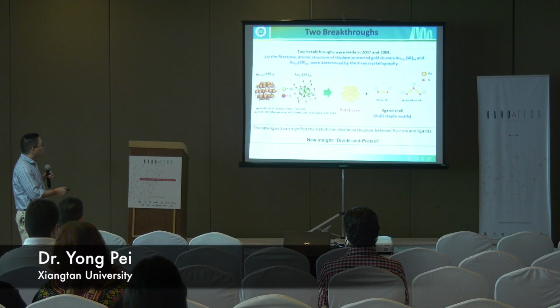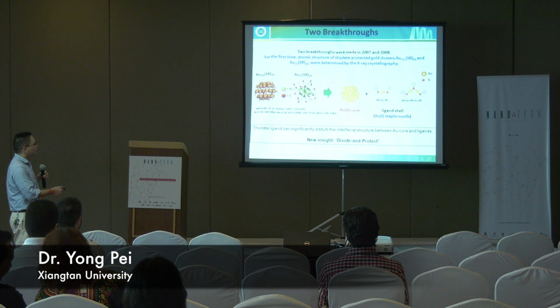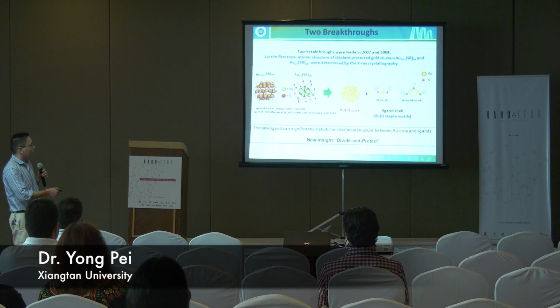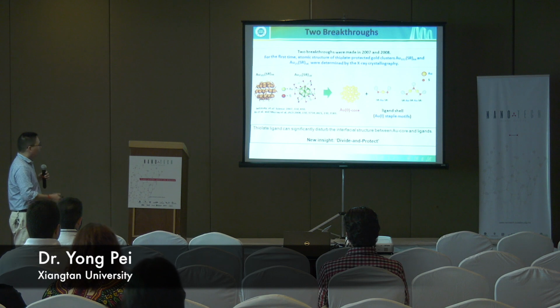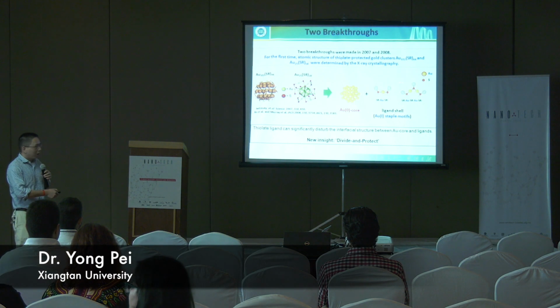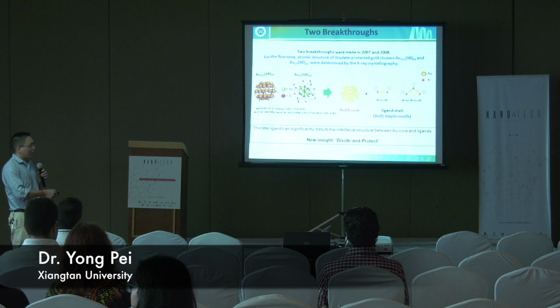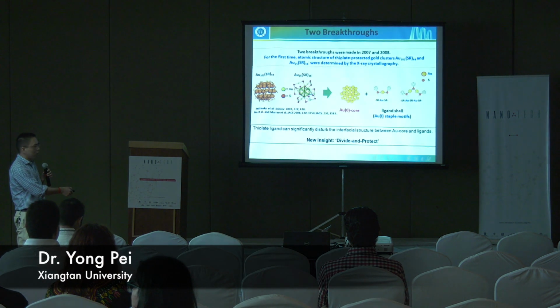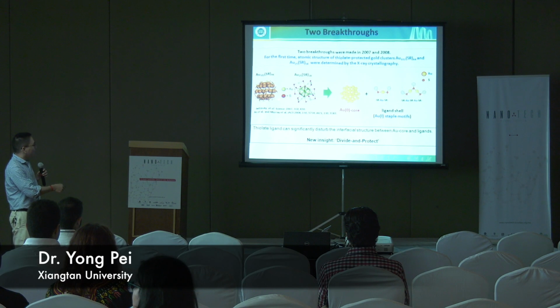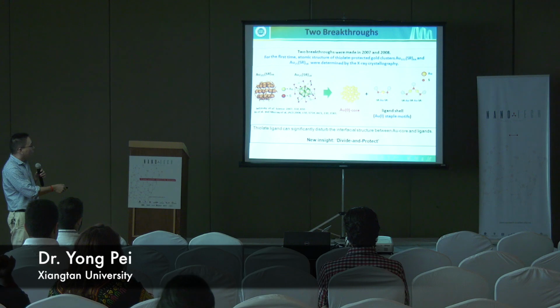But in 2007 and 2008, there were two breakthroughs in determining the structures of thiolate-protected gold clusters, including Au102 and Au25. These are the two most famous clusters. Surprisingly, from the crystal structures, we found that in both clusters they formed a new kind of ligand motif. Now we know it is called a staple motif because the shape is like staples. This cluster can be divided into a zero-valence metal core and a ligand shell containing Au(I), a gold atom between two thiolate ligands.